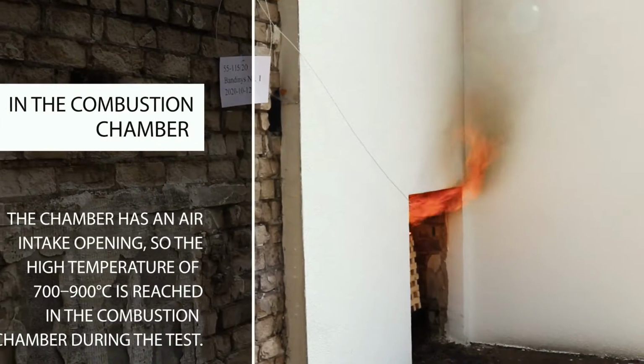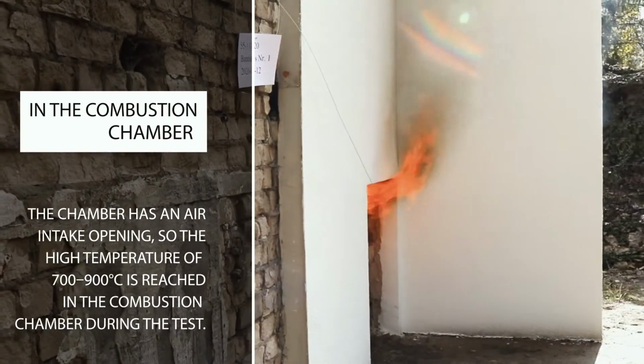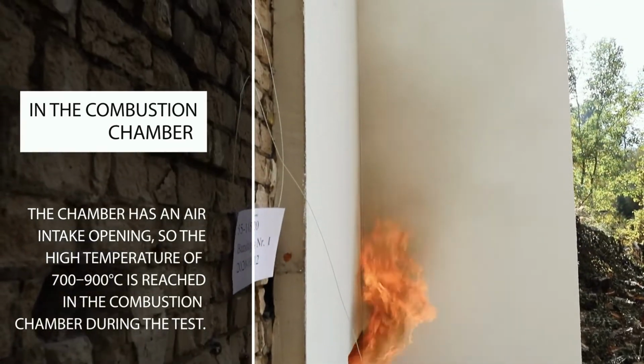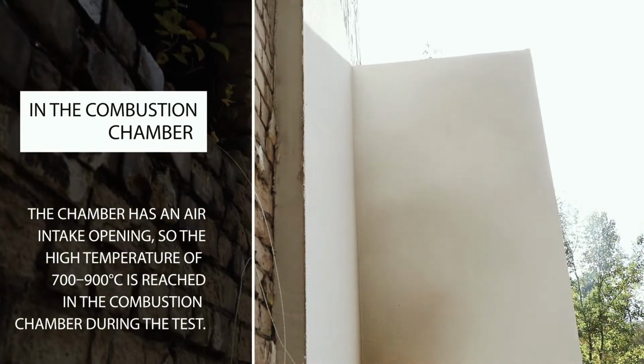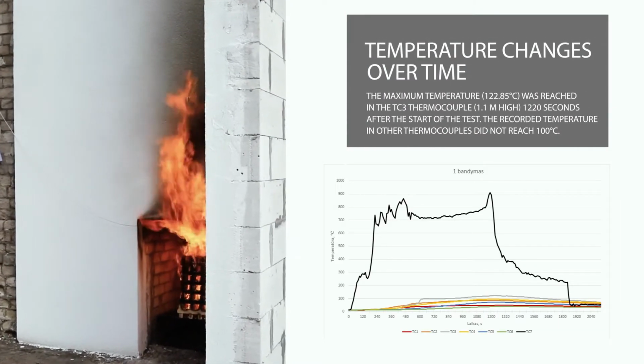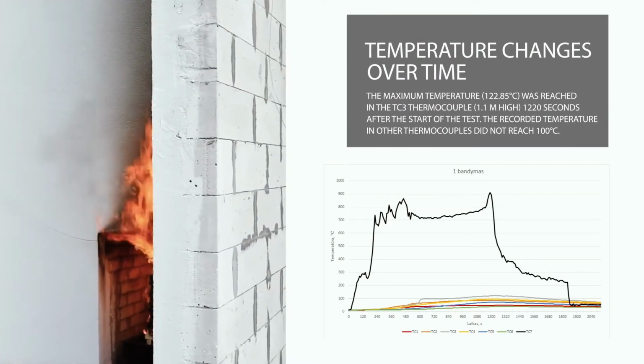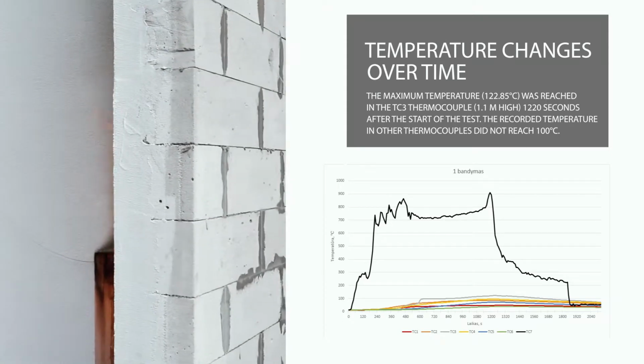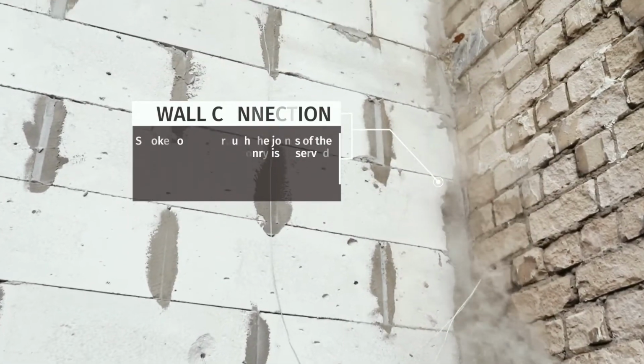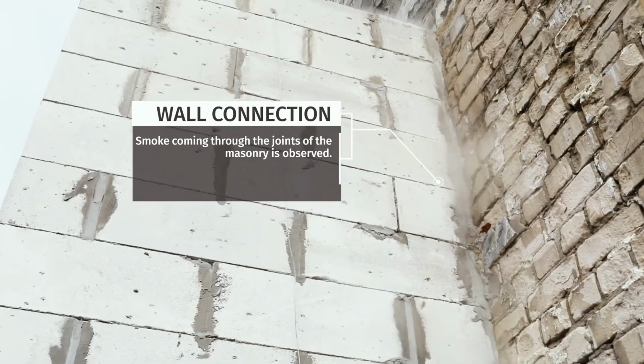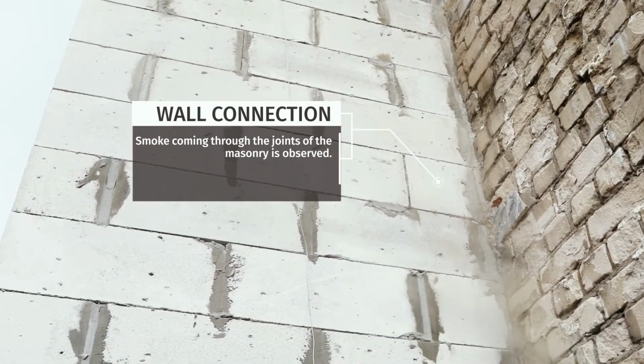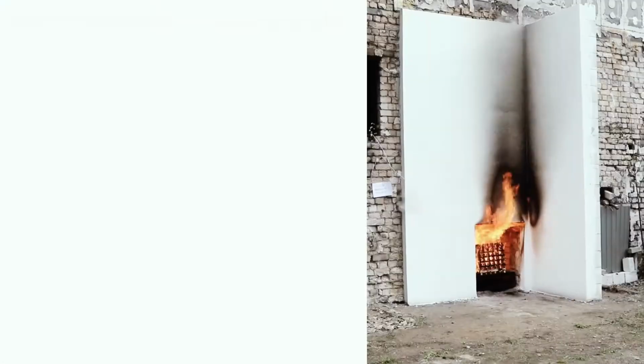The combustion chamber has an air intake, so the temperature in the combustion chamber reaches some 700 to 900 degrees during the test. The diagram shows that the maximum temperature exceeding 122 degrees Celsius is reached in the TC3 thermocouple about 20 minutes after the start of the test. The temperature in the other thermocouples did not reach 100 degrees Celsius.